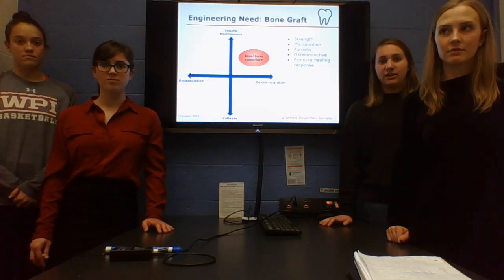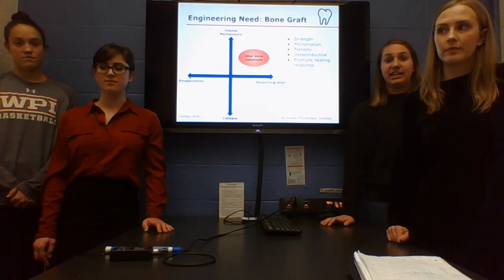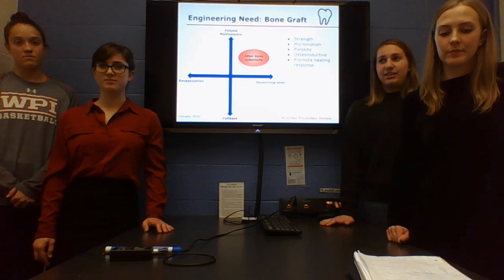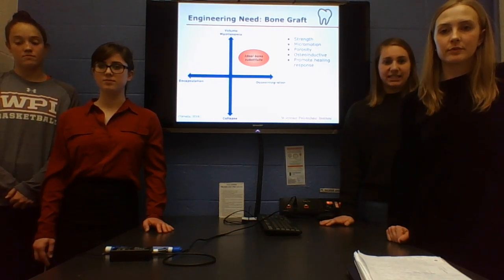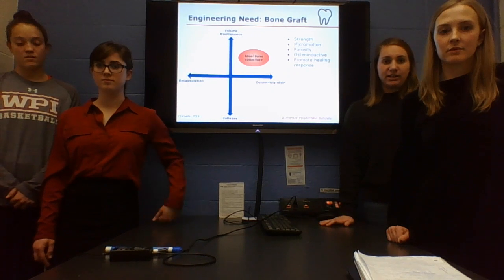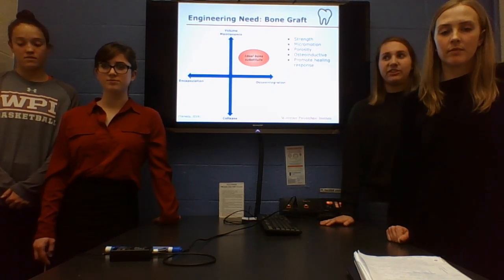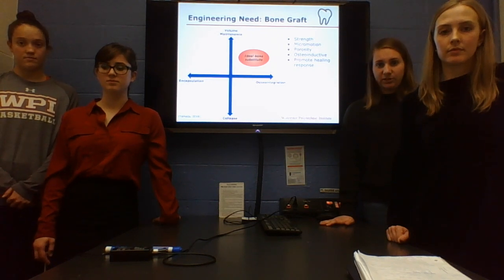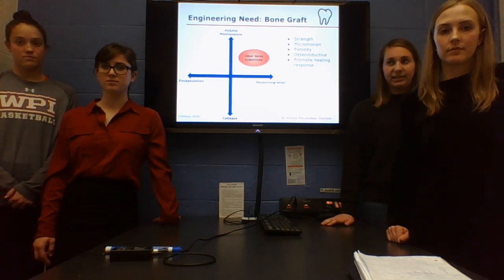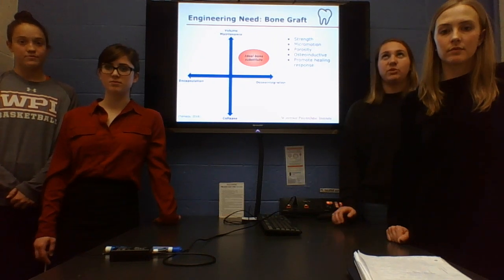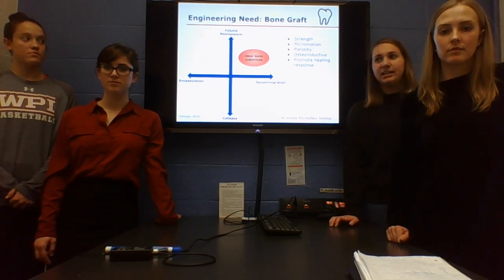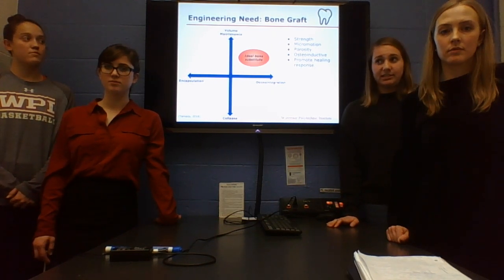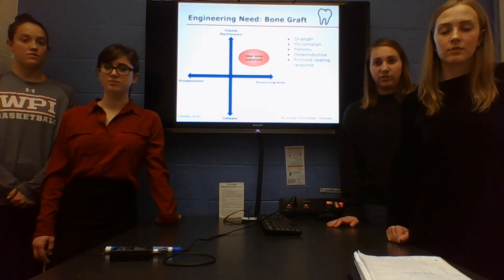In addition, there are a number of other engineering criteria that the ideal bone graft must meet. Firstly, it must have the mechanical resistance to maintain the space at the extraction site, and this will also promote a larger volume of regenerated bone. Additionally, it must prevent excess micromotion. If there's too much micromotion at the healing site, the bone graft will become fibrously encapsulated. A small amount of micromotion, approximately 20 to 50 microns, is beneficial to bone formation and growth.